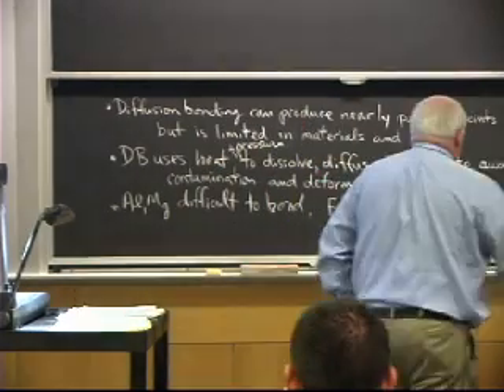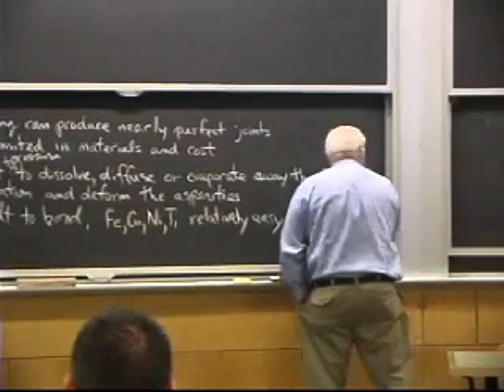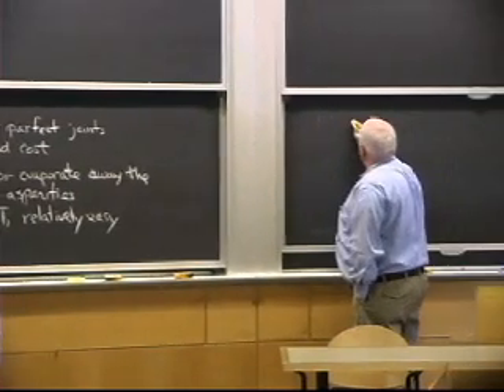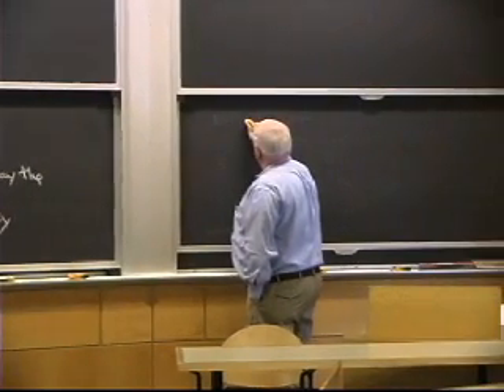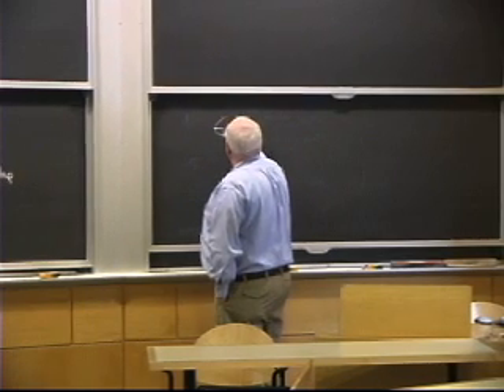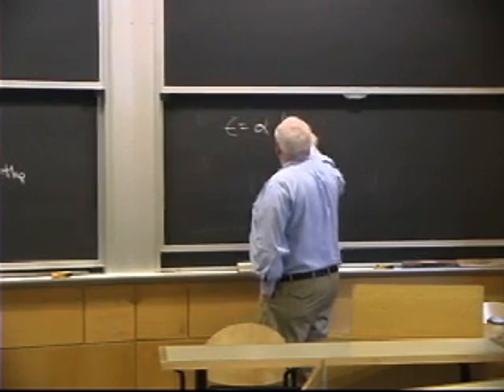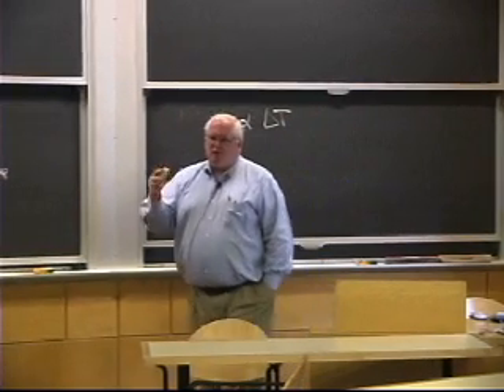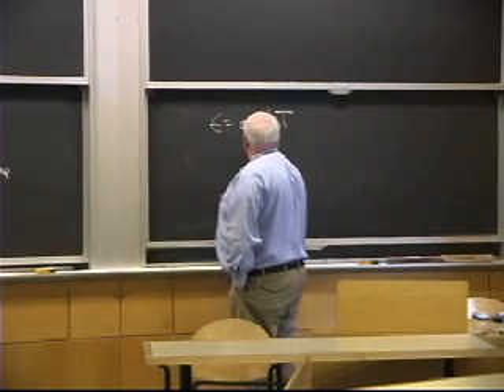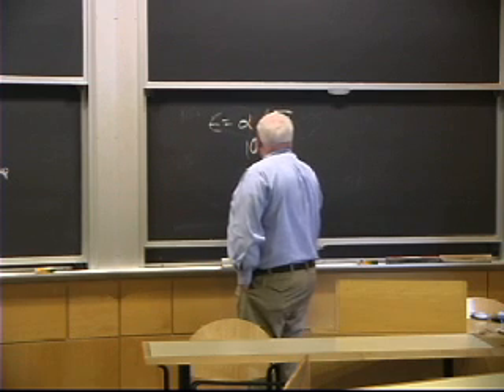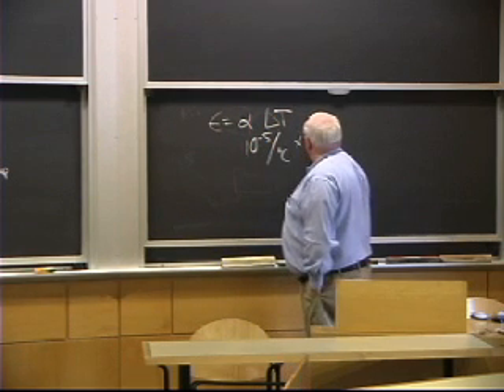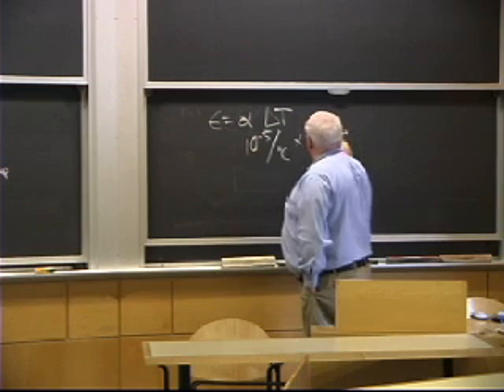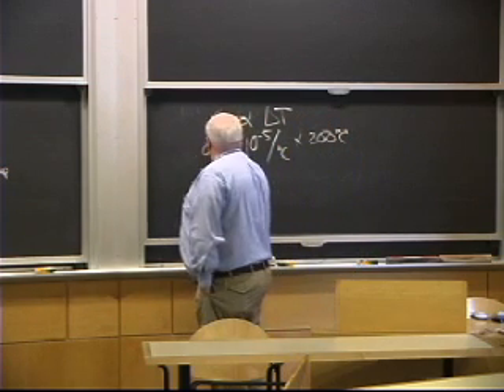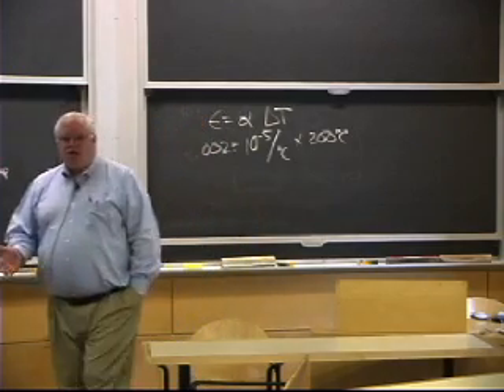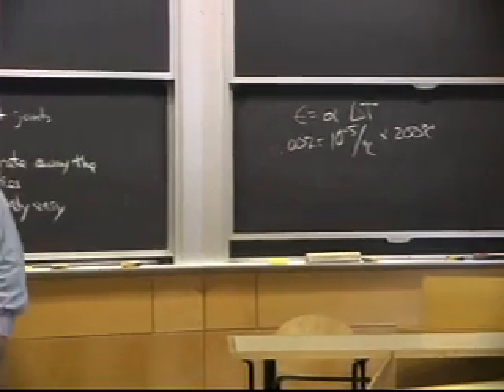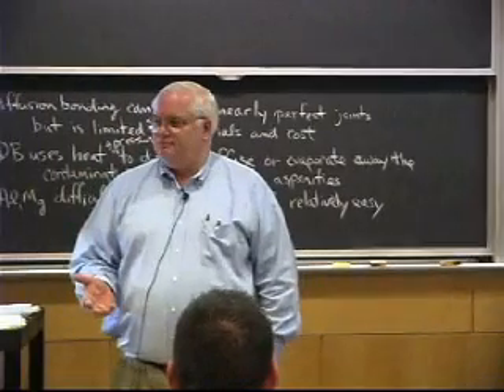And it turns out you only need about 300 degrees Fahrenheit, or actually, let's call it 200 degrees. If I know that the strain is equal to the thermal expansion times delta T, it turns out the thermal expansion difference between a metal and a ceramic is something on the order of 10 to the minus 5 per degree C. Well, if I have 10 to the minus 5 per degree C and I multiply by 200 degrees C as a delta T, I end up with a strain of 0.002. What do you know about a strain of 0.002, or 0.2%? That's the yield strength of the material, right?